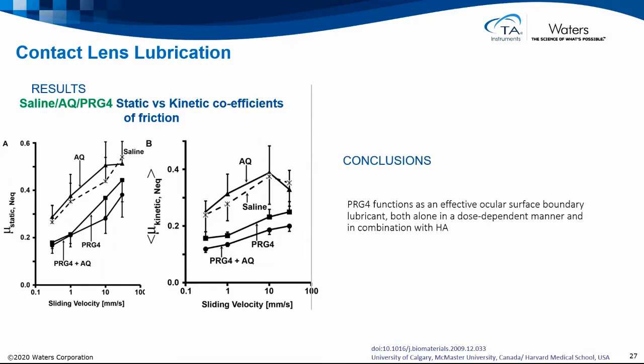Okay, so here we see a final set of plots. Again, static friction, kinetic friction against sliding velocity. And here we have an addition of this AQ parameter. AQ is an off-the-shelf hyaluronic acid. And what we see is when you combine proteoglycan 4 with that solution, you get not only the benefit from proteoglycan 4, which is quite a bit less, but on the kinetic friction, even lower friction still. So that combination looks like a very powerful advantage, especially relative to saline solution or this standard hyaluronic acid solution, something like half the friction values in these plots.